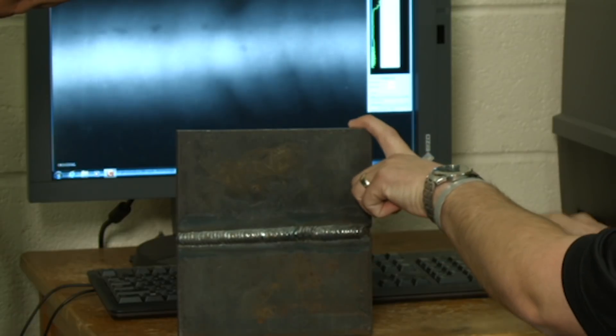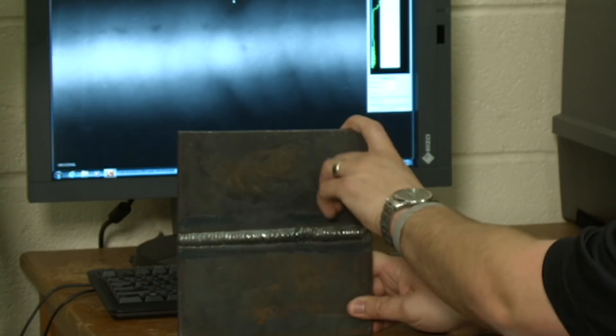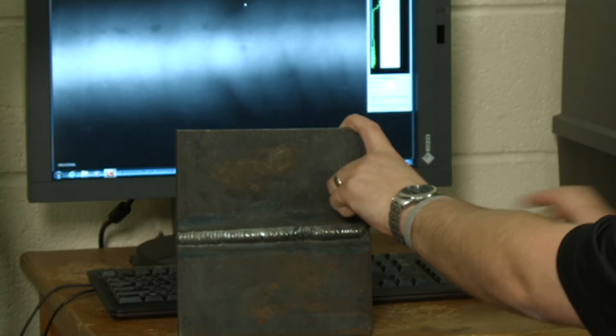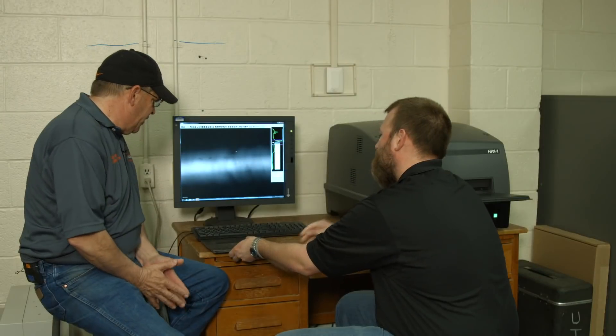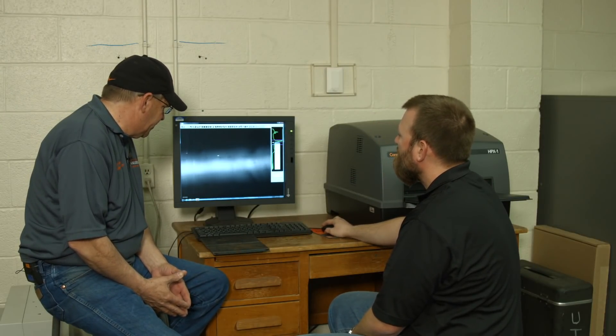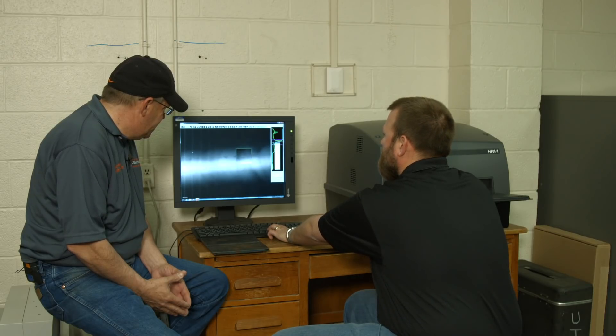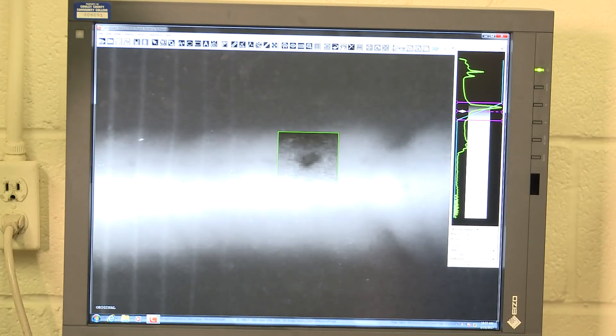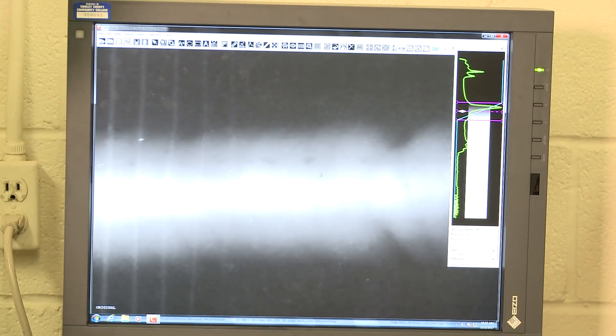Right here where my mouse is, that's that U or V right in this area. That gives us a good place to say these defects, starting to appear just to the left of that U or V, occur right in this area — embedded in the weld next to the toe. From experience, I would say those are glass or silicon deposits and we need to go dig those out. Looking through here, that's a pretty dark area and you can see it's starting to look a little grainy, but it's not perfectly round. That one's elongated and has some shape to it other than being round. That's a good way for us to say it's going to be something like a slag inclusion — you guys might call it by a different name.